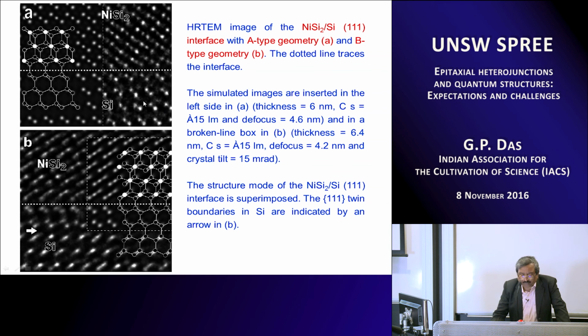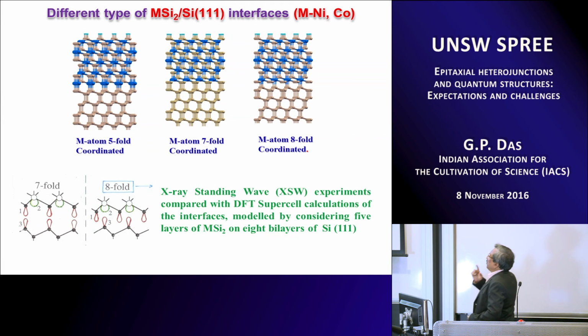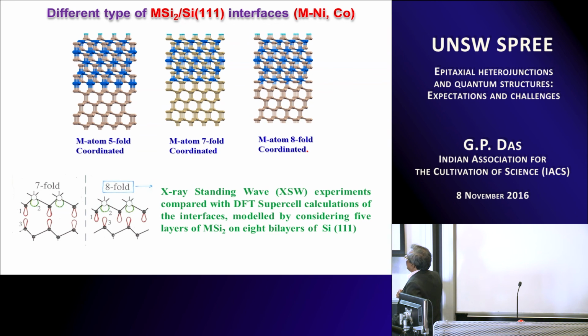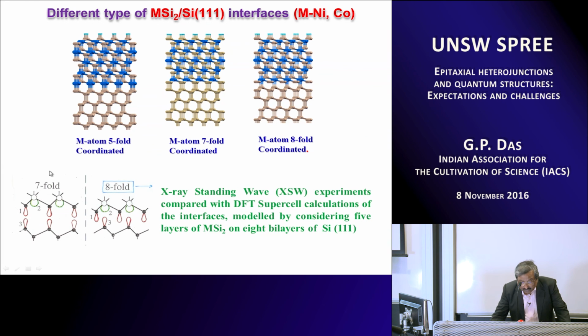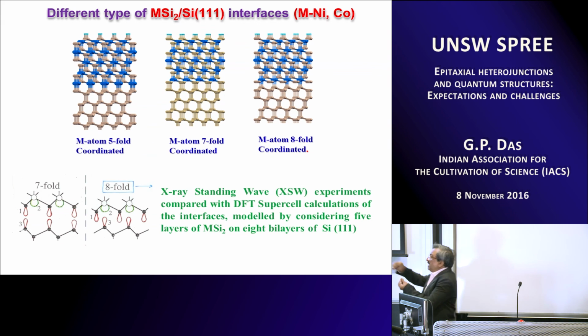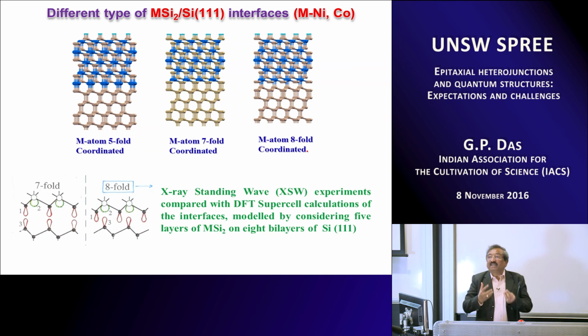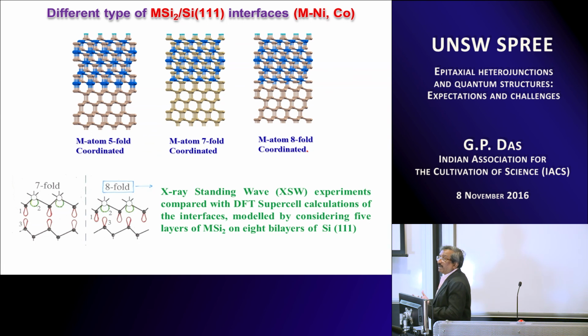And we have done a DFT calculation for both these interfaces to calculate the Schottky barrier height. Before I tell you the result, something is very important, namely, what is the interface structure? At the interface, it is possible that the metal atom, what is the metal atom here? It is nickel. The metal atom, which is in this particular case the blue one, is bonded to the silicon. Here, the silicon of NiSi2 is bonded to silicon of silicon 111. So there is a difference between this and this. It is called 5-fold coordinated surface, 7-fold coordinated surface, and 8-fold coordinated surface, which essentially means how many nearest neighbor atoms are there for the metal. That makes a difference in the Schottky barrier height.